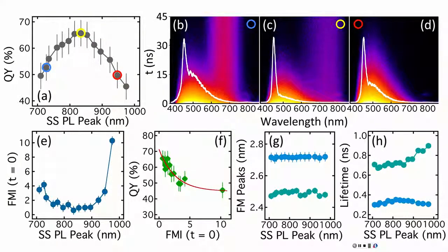The interesting thing about these materials is they've never been exposed to oxygen, so when we do gap versus size, we're the first paper that's ever seen excellent agreement with effective mass approximation. Everybody else's dots have been oxidized already. There's a PRB from 1995 by a couple of Japanese guys, the first ones to do this for silicon. I take the curve right out of their paper, put it on top of my data, and the agreement is almost uncanny. Okay, so that means EMA is a good approximation, but what does EMA say about this?